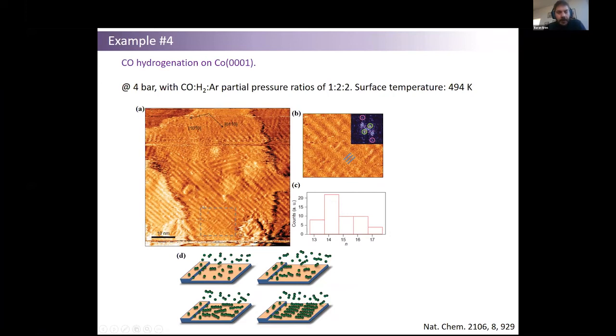And you see on the cobalt surface the formation of these structures. And here you can see a zoomed in image. And these structures that are resolved are attributed to the formation of linear hydrocarbons. So these are your products actually. And you can see that they're mostly perpendicular to the step edges. Now this paper that is discussed in the review article also mentions the reaction mechanism.